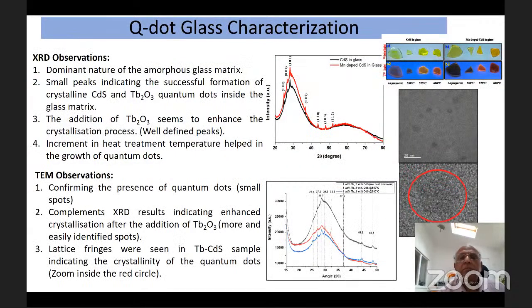As mentioned before, we calculated the quantum dot size distribution using the X-ray powder diffraction technique for both types of quantum dot containing glass, CdS glasses and terbium doped CdS glasses. We also utilize TEM techniques where you can see the quantum dots, and the average size of the quantum dots is well below 5 nanometers.